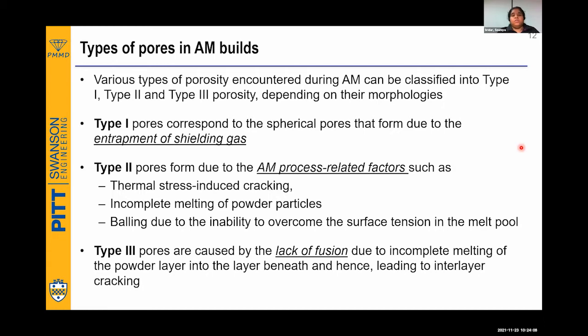But the good news about this type of pores is that they are typically not detrimental, for two reasons. One, they are spherical, so spherical pores are not a serious issue. And secondly, they are only a few nanometers to micrometers in size. They are not very huge pores. Even if we do several processes to remove porosity, removing type 1 pores is not so simple because of their small size. But still, since they are not too huge and their shape is such that they don't act as local stress raisers, it is not a serious issue with type 1.